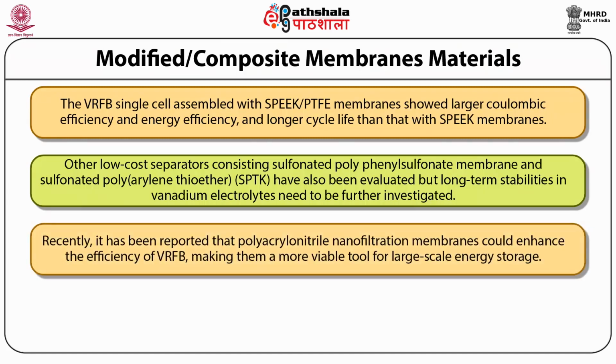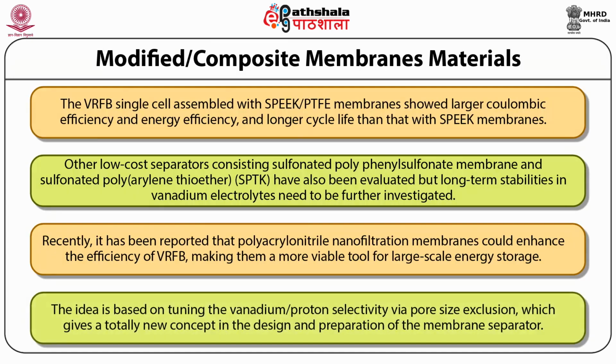Recently, it has been reported that polyacrylonitrile nanofiltration membranes could enhance the efficiency of VRFB, making them a more viable tool for large-scale energy storage. Now here the idea is based on tuning the vanadium proton selectivity via pore size exclusion, which gives a totally new concept in the design and the preparation of the membrane separator.